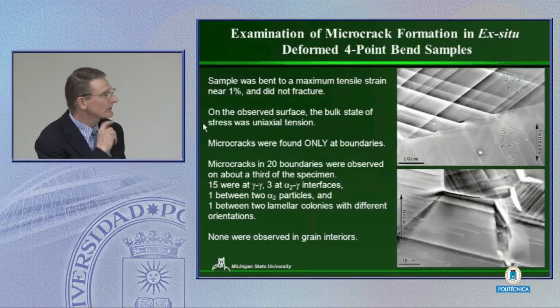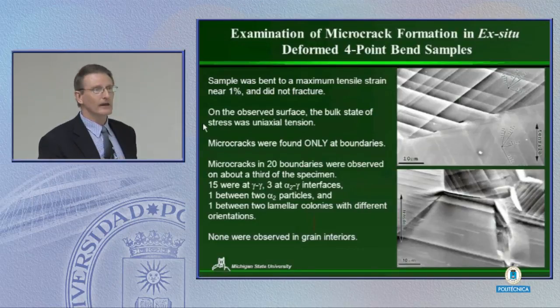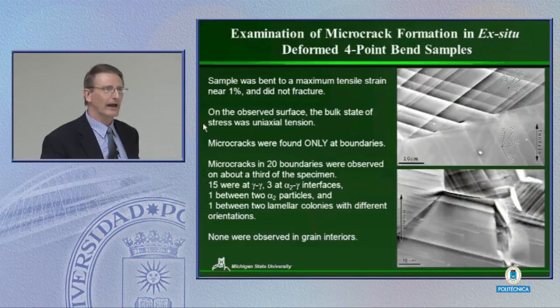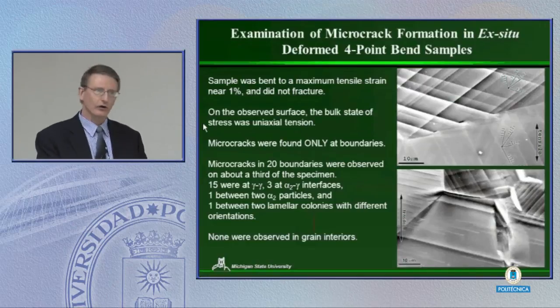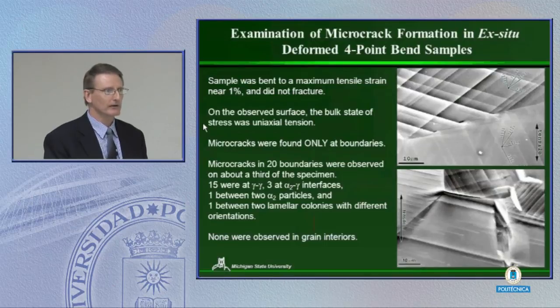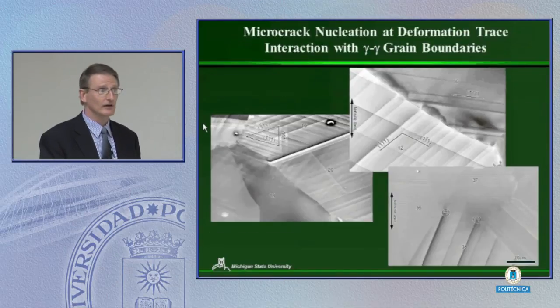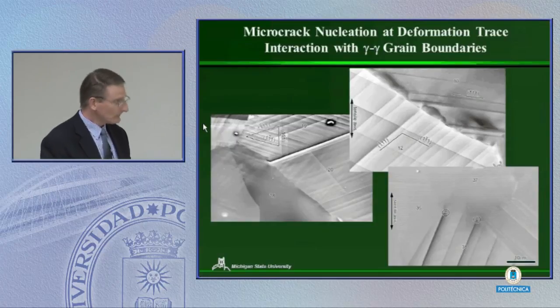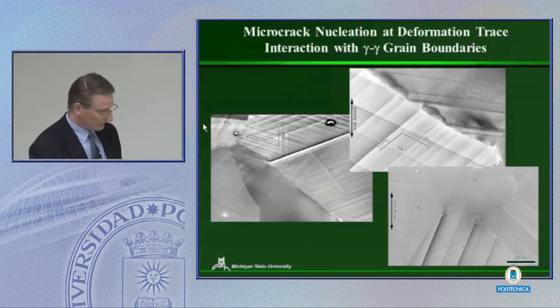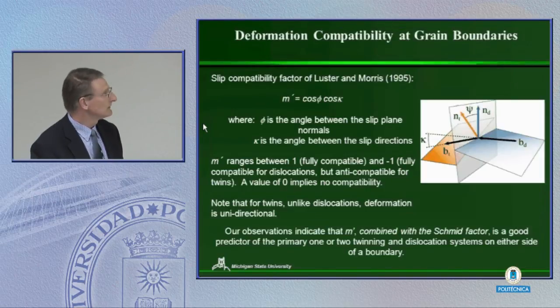And really the question comes up is, why do specific boundaries crack and other ones don't? We have twins interaction with the grain boundaries. Are there good grain boundaries and bad grain boundaries? And if we can understand what are the good grain boundaries and the bad grain boundaries, maybe we can do something in processing to eliminate the bad grain boundaries. So again, here are just some more examples of these. We can see these little tiny microcracks here, the microcracks there.